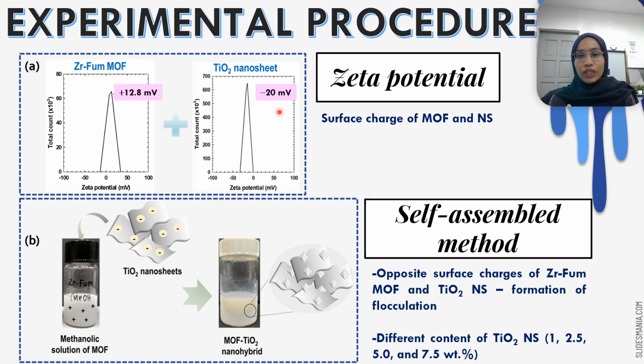This is what we call the self-assembly method. After they are mixed together, they form flocculations. We can see a precipitate from here, and this precipitate we call a nanohybrid. In order to study the effect of the TiO2 nanosheets on the performance of these materials, I use different contents of the TiO2 nanosheets, from 1 weight percent up to 7.5 weight percent.